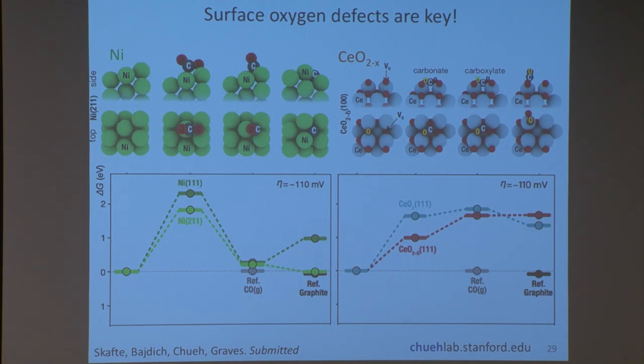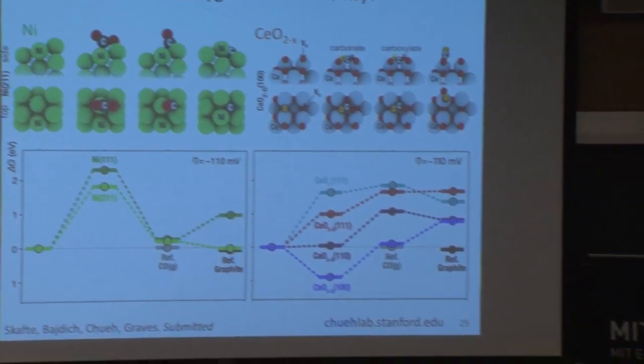And if you continue to go down to different crystallographic orientation, at some point you encounter this particular arrangement, which is the 1O termination of this crystal. And you can see it's actually exactly the opposite of nickel. So rather than having an energetic barrier for CO2 to adsorb onto the surface, which is the key reactant, it's actually downhill by almost 1 electron volt. Okay, this is the free energy. So that means there will be a lot of carbonate on the surface, and that's exactly what we see experimentally. We see a lot of carbonate on the surface.